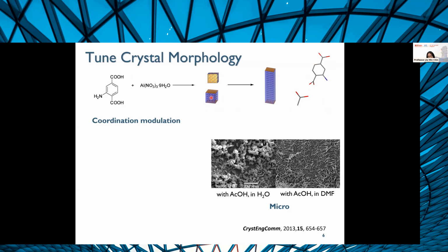And so it inhibits the growth of these facets more so than the growth of the purple facets. And what happens is that you not only slow down the growth of the MOF, but you also end up with crystals of different aspect ratios. So we found that if you take these materials and you throw in 30 equivalents of acetic acid, depending on which solvent you use, you get completely different types of morphology. So in water, you do get rod-shaped crystals, but they don't have as high an aspect ratio as if you had them in DMF.